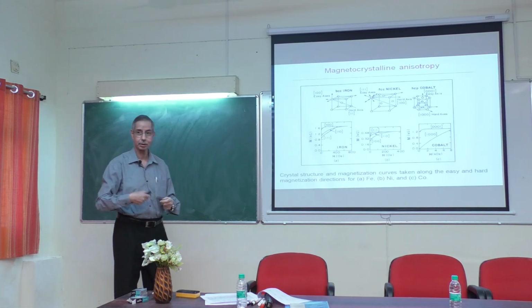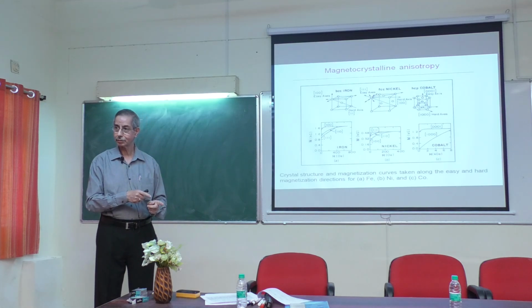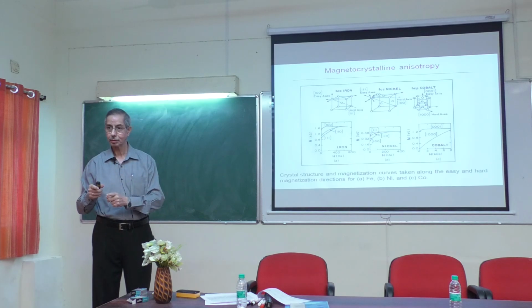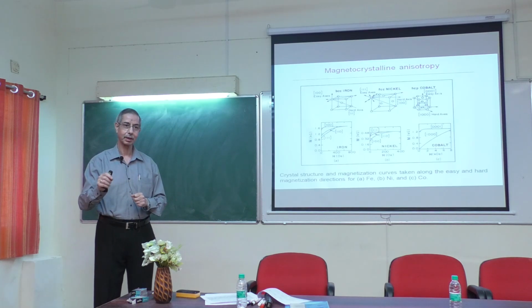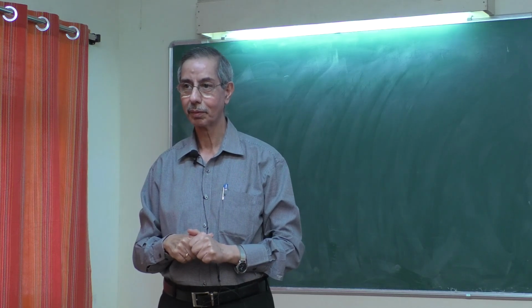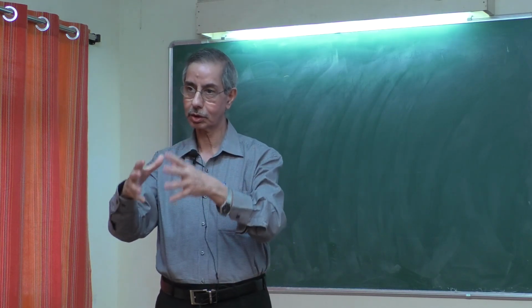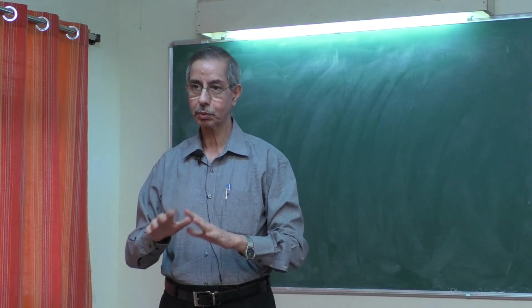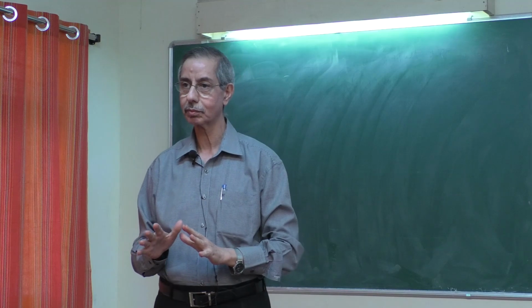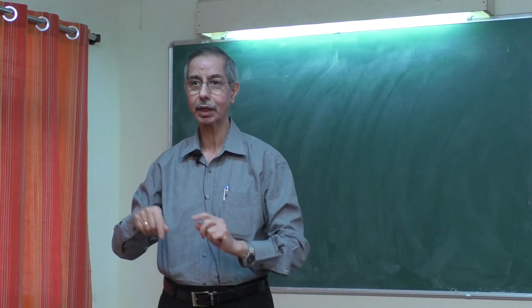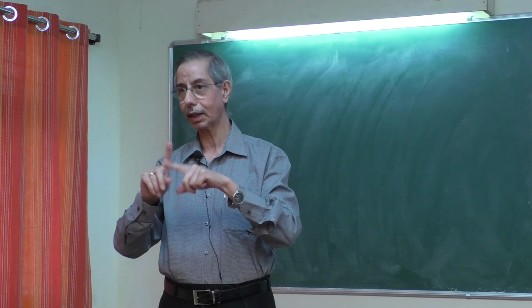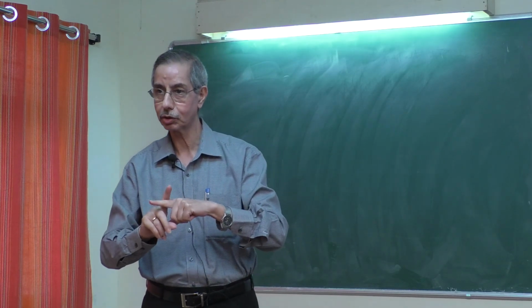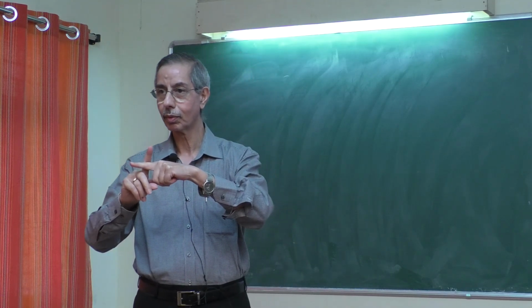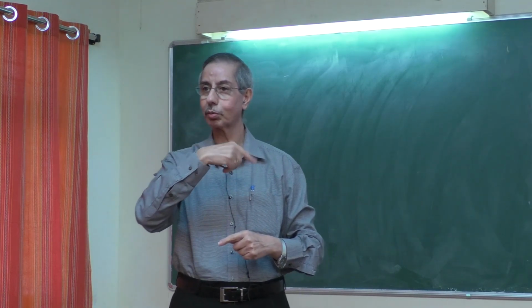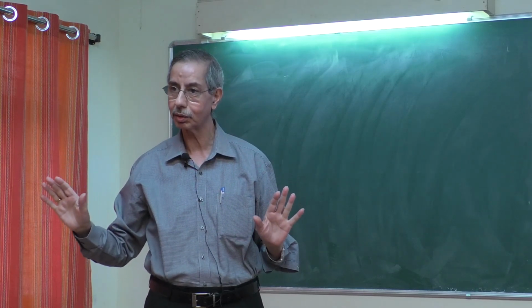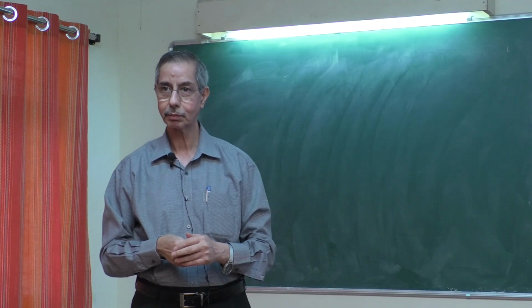So that means the anisotropy, as you go from iron to nickel, shows a slight decrease, and then looking at magnetization, right? Now the crystalline electric field is already there. It is present and it has the same symmetry as that of the lattice. So if it is in a certain direction, it locks the orbital angular momentum, and hence the orbit. And if the spin orbit coupling is strong, then it locks the spin direction also. So now the spin direction is along some crystallographic axis, which is there in the absence of any external magnetic field. Is this clear?